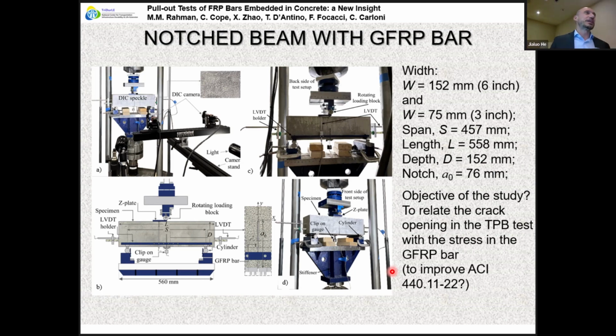So we tried to consider another point. There is a lot of discussion now in ACI about the opening of the cracks with these bars. It shouldn't be as important as with the steel bars because there is no corrosion, but it's still a parameter to check when you do the design. So we came up with a new test method. Basically, it's a beam with the bar inside and a notch, and it's tested in 3-point bending. You can see here, the bar actually extends at the two ends to measure the end slip or displacement. We use digital image correlation.